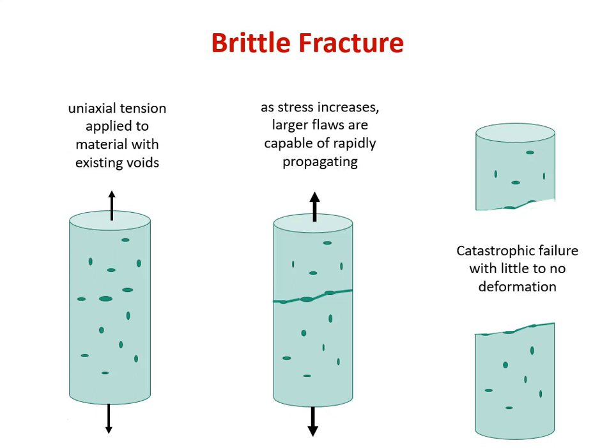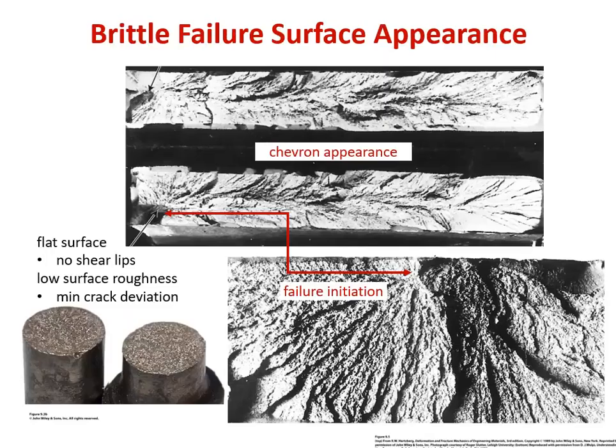So these are the steps to brittle fracture. And you can see that even though the ductile fracture, the ductile failure, and the brittle both involved pre-existing flaws, the little microvoids in the case of the ductile microvoid coalescence, and these little green pre-existing flaws that we're showing schematically on this diagram, they both involve pre-existing flaws. But in the case of the brittle fracture material, most of the failure onset in terms of the applied stress was really more of a function of the size of those flaws and their orientation relative to the applied stress. There wasn't anything else to absorb the energy we put into the material, so it was much more important what those flaw sizes were. And of course, we had no warning.